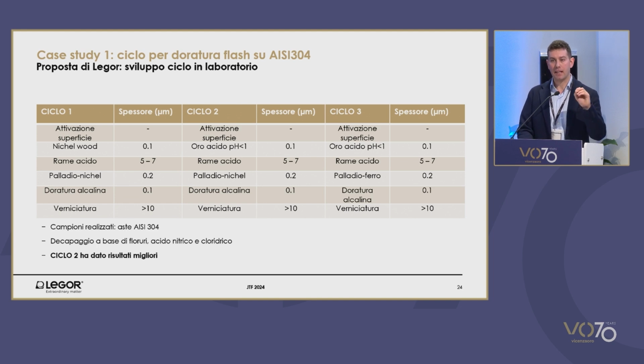In the first cycle, we wanted to make sure that the release of nickel was only due to the nickel layering, or if the underlying metal was releasing nickel. In cycle 2, we used palladium. In cycle 3, we only used nickel-free layers, and it was palladium iron that was used.